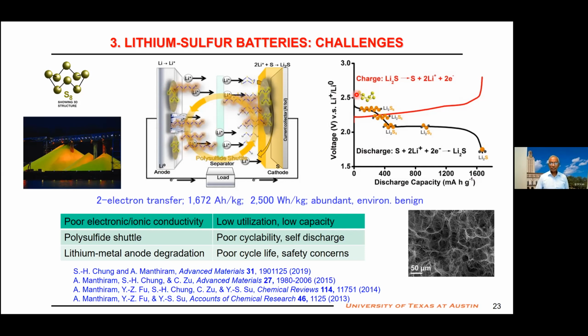Second, we start with sulfur, that is an S8 ring molecule. When you discharge it, you break one bond, we form Li2S8, Li2S6, Li2S4, then finally Li2S2. The end product Li2S is insoluble in the electrolyte, but the intermediates, the linear ones, are all soluble in the ether electrolytes we use. So when they are soluble, they go from the cathode through the porous separator to the anode, messing around with the cathode as well as the anode. That is called polysulfide shuttle. It's going back and forth between the 2 electrodes.